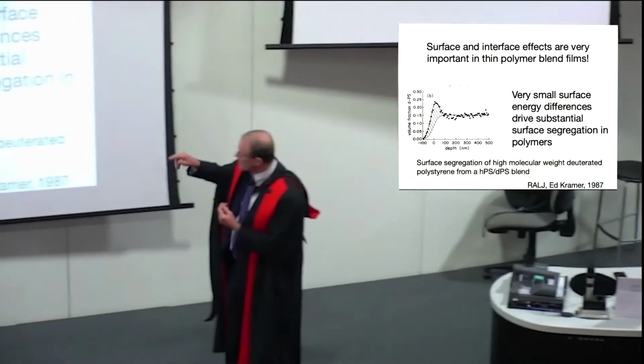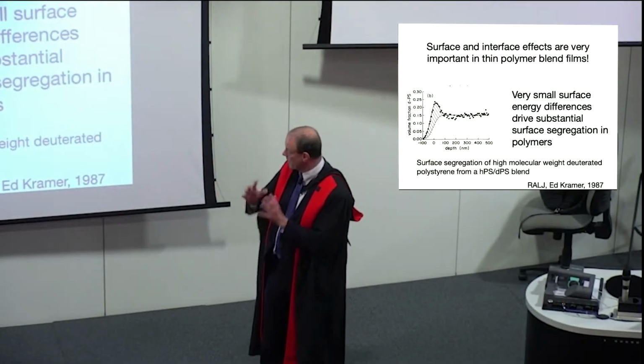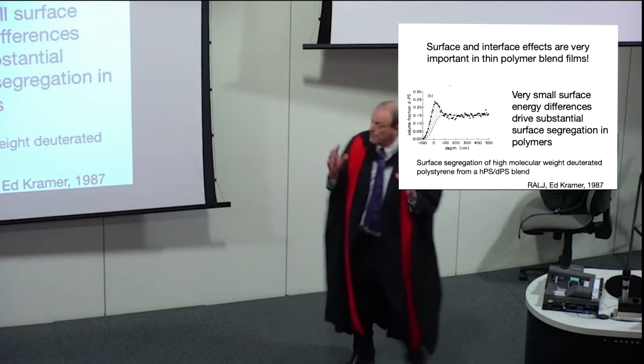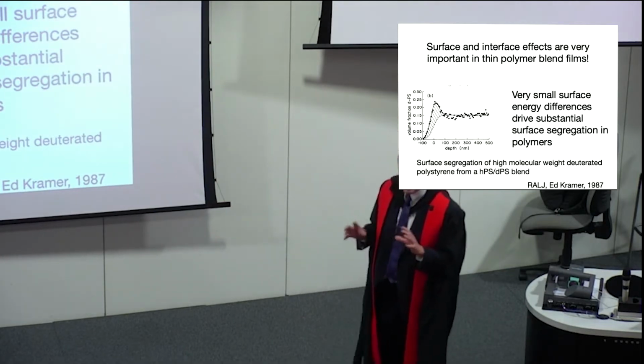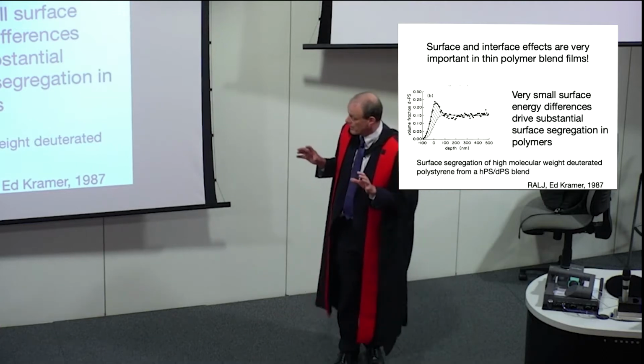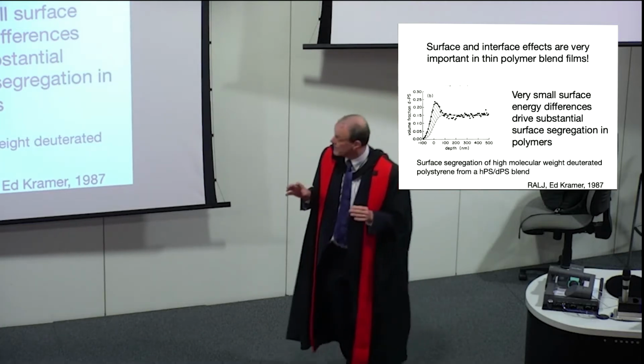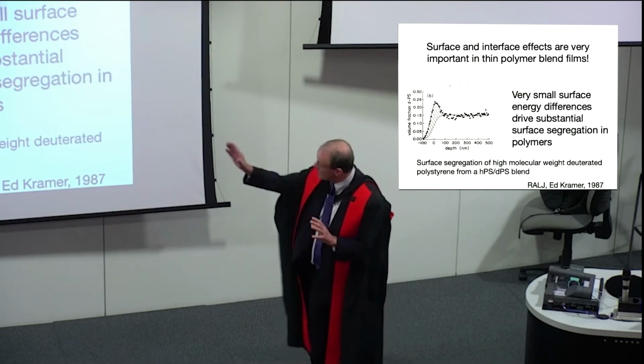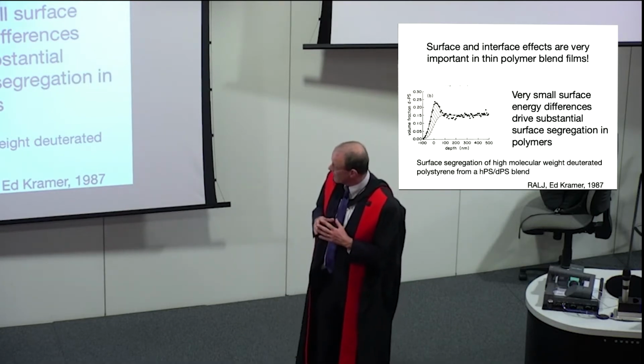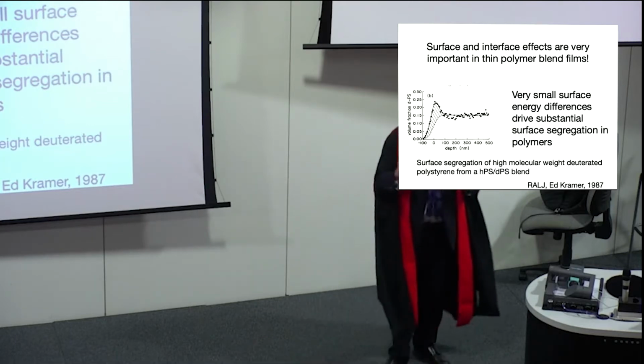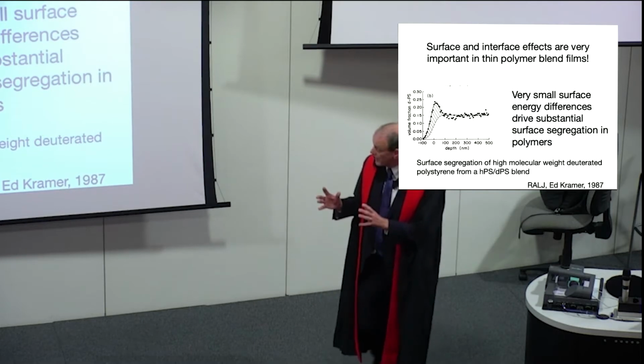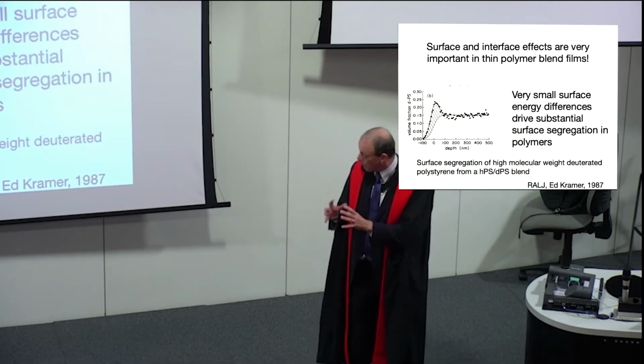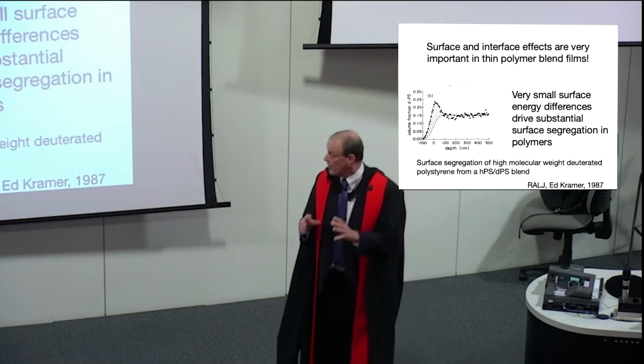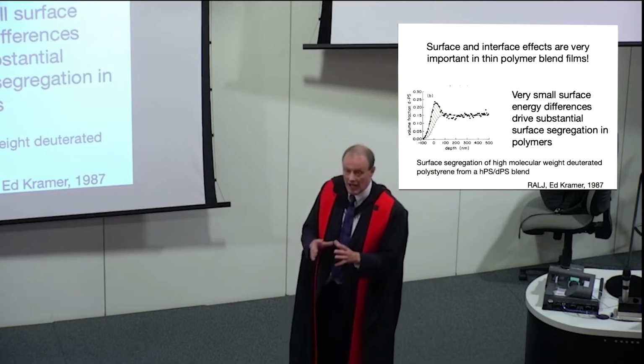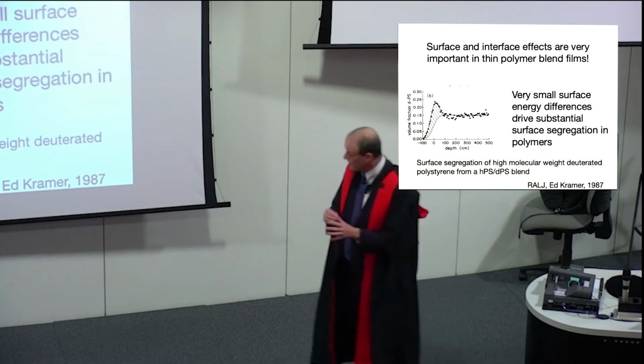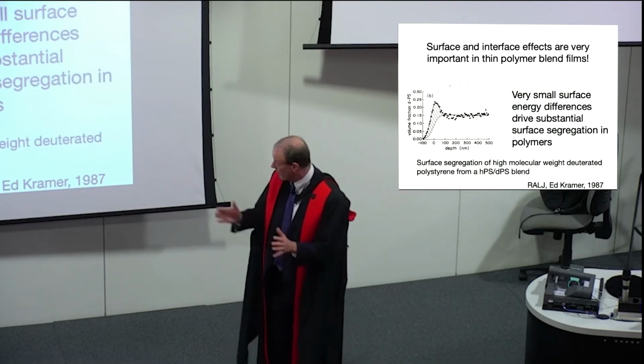So what we found here was, in this case, the only difference between these two polymers is one's hydrogenated and one's deuterated. So it's simply the difference between a CH bond and a CD bond. A very small polarizability difference, probably worth less than 0.1 dynes per centimetre in terms of surface energy. This isn't enough to make the deuterated stuff go to the surface. So for reasons that we understand, that I won't have time to go into, the polymeric nature really amplifies both the scale of the size of the effect, how much segregation you get for a given surface energy difference, but also the length scale, how far into the bulk that goes.